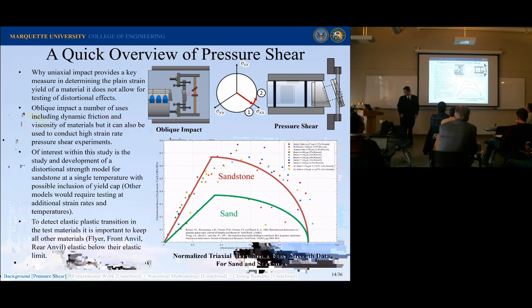The specific test that I want to do is pressure shear, and what we're going to do is we're going to take a flyer and we're going to impact another material. So we have our system right here. We've got a sabot and a piece of metal on the front, and then we're going to impact the material at an angle. And based on the wave structure, we're going to first load it in pressure, then in shear, and then we're going to get our yield surface. It's really difficult to do it one way. If we tried to load it in shear first, because the shear wave is always slower than the longitudinal wave. So you first got to load it longitudinally, then in shear. So that's how we're going to get there onto our yield surface and populate our curve.